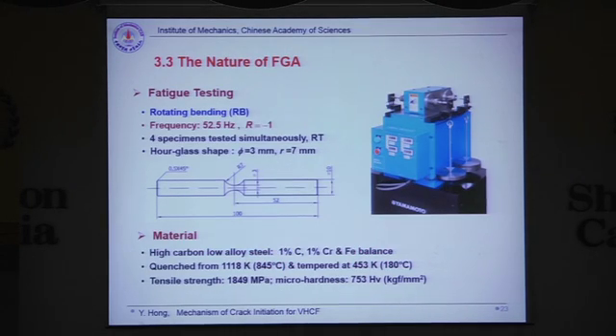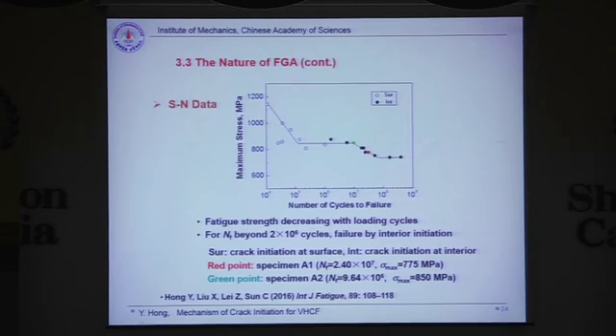Therefore, we try to reveal what is the real nature of this very important region that consumes so large a part of fatigue life. We use the ordinary rotating bending method, with a stress ratio of -1, and use a high strength steel for this testing. And from this data, we choose two specimens for detailed observations. It's the green one and the red one.